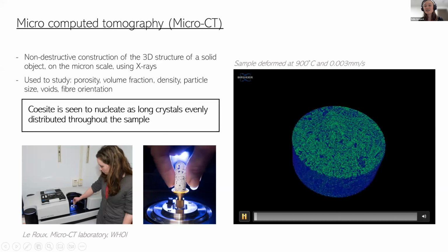When they hit the detector, they give you a 2D image. And by doing very, very small rotations of the sample, you're able to collect successive amounts of these 2D images and then construct the 3D structure of the rock. And that gives you stuff such as volume fraction, density of the particles and everything. So what we're interested in is looking at how homogeneous our microstructure is and to give us an idea of where we want to section the rock.